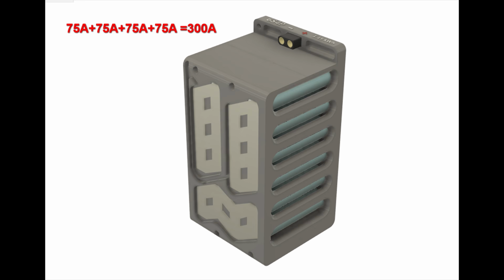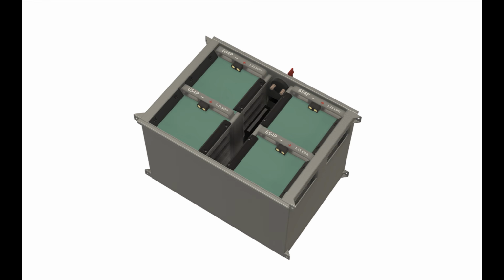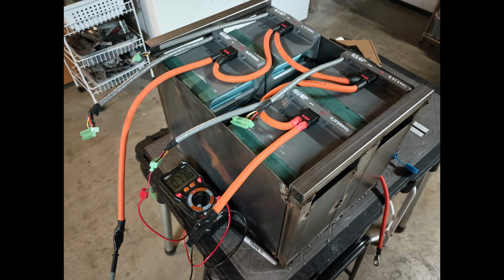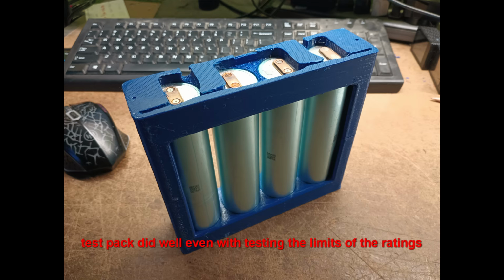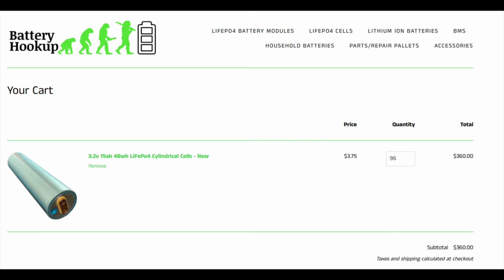Knowing this, I arranged the cells into parallel groups of 4 to provide burst currents up to 300 amps, and put 24 of these banks in series to make a peak voltage of 87.6 volts at full charge. A 24 series 4 parallel pack seemed like it would work well for my systems, so after a test batch, I ordered 96 more cells.